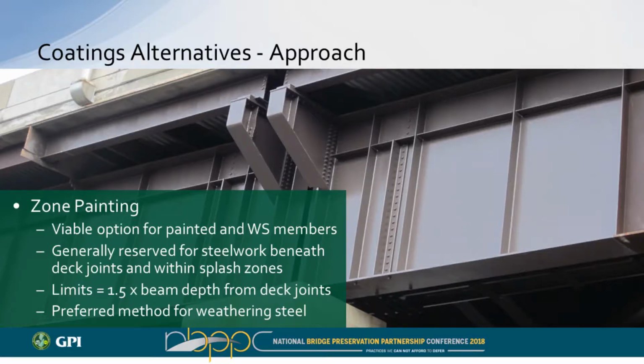The Turnpike Authority likes to use about 1.5 times the beam depth for the extent of that zone. Sometimes, as you can see in the photo here, we actually took it out to this stiffener to have a nice clean cut line rather than just a cut line out on the beam itself. But generally speaking, it's about 1.5 times the depth, and it is the preferred, really the only method for the weathering steel. So what do we go with for our painted bridges?